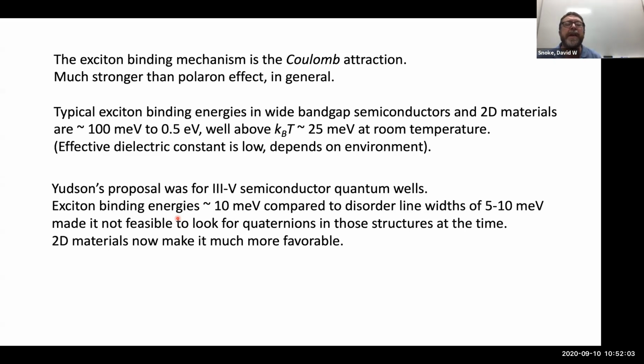But what got me interested last year is just thinking about these 2D materials now, where the scale of the energies is completely different compared to what we had back in the 90s when Yudson made his proposal. Typical exciton binding energies are 100 millielectron volts up to half an electron volt. And so the quaternion binding energy, you expect to be some fraction of the exciton binding energy. So it's not really standing on your head to get quaternion binding energies that are already up at 25 millielectron volts or more and become therefore feasible at room temperature.